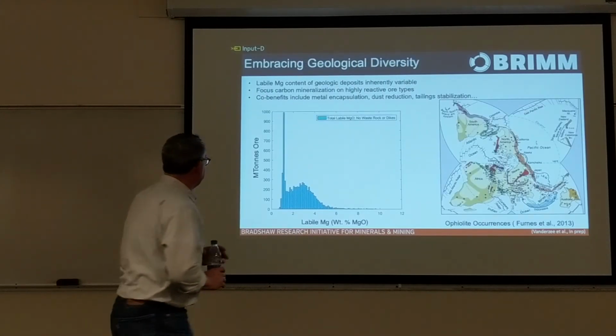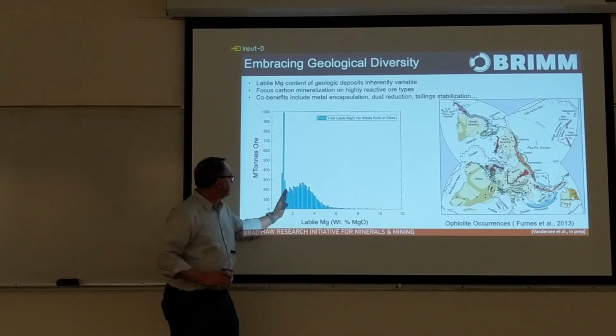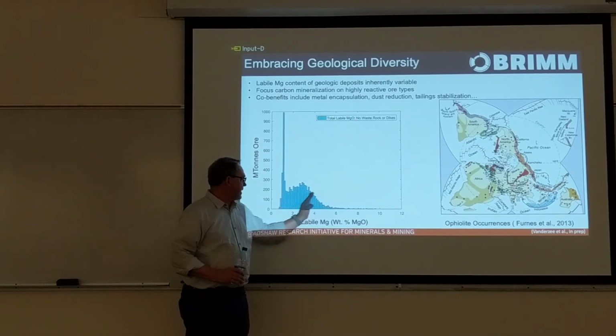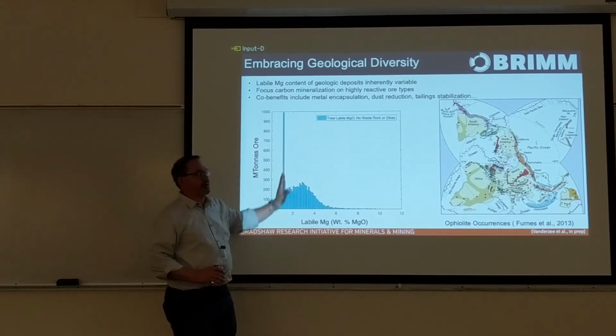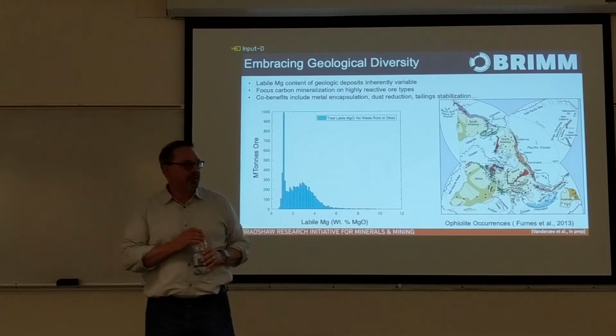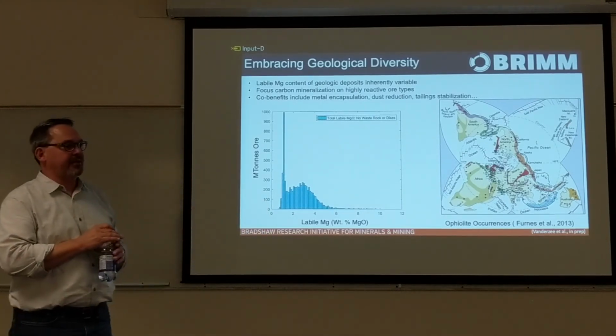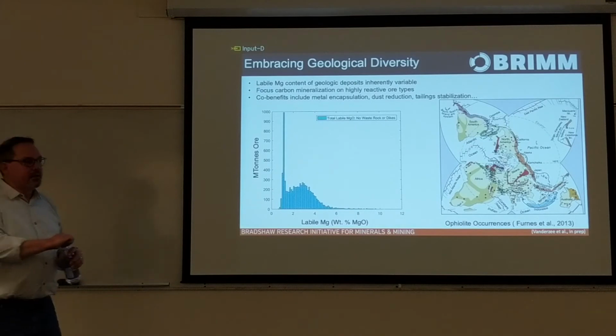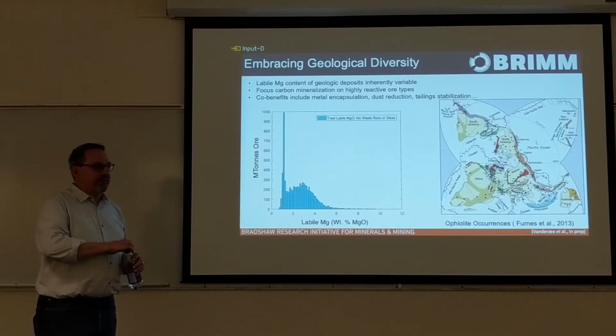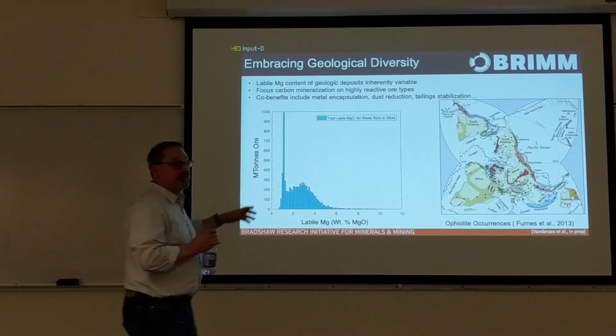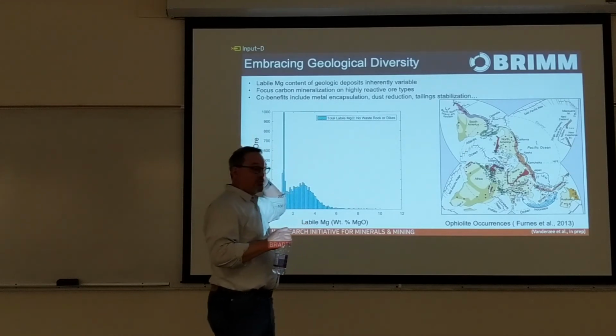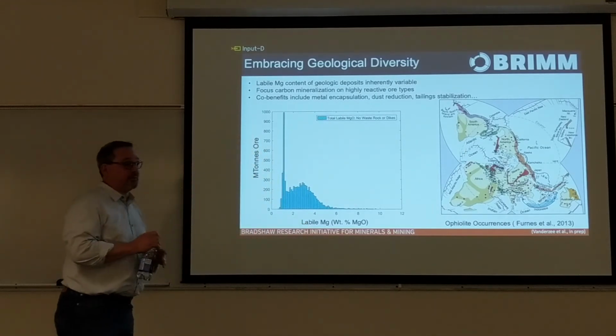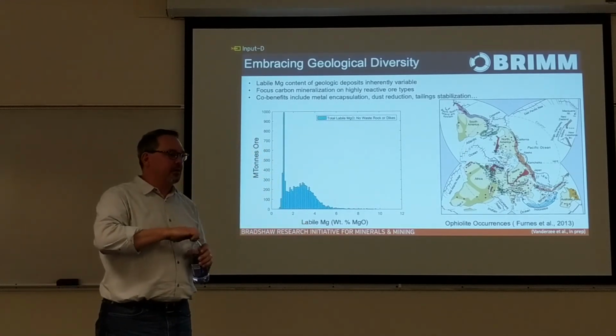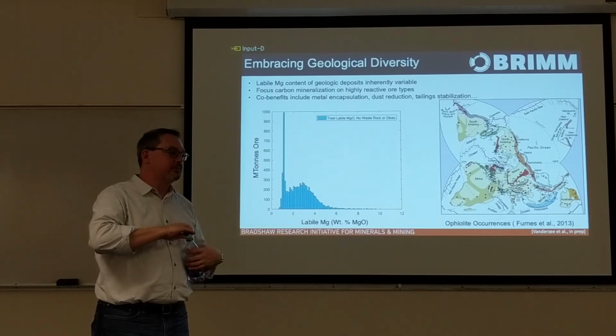Yeah, I mean if you look at this plot, this end of the spectrum is brucite, and this big peak down here is essentially brucite-free material. So it gives you a sense of what exists in the major minerals. But yeah, for this deposit, it's brucite. In some cases, it's hydrotalcite group minerals, which are common at Mount Keith, for example, and they have similar dissolution kinetics. But brucite is the most common one.